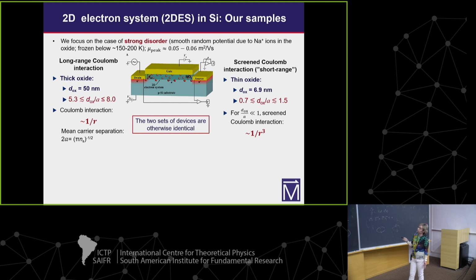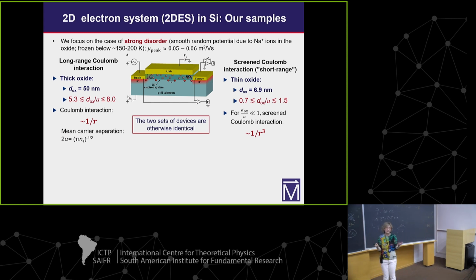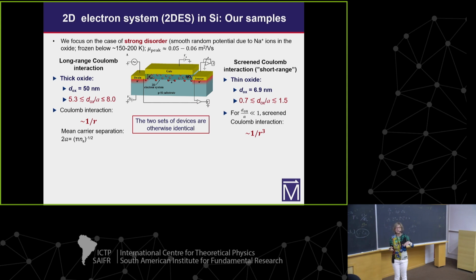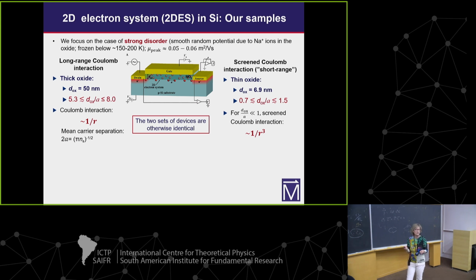I want to emphasize that these two sets of devices were fabricated literally simultaneously. Every single step out of more than 100 steps of fabrication is identical except for the thickness of the oxide, so that any difference between the behavior of these two systems that we see must be due only to the effect of the range of the interaction.